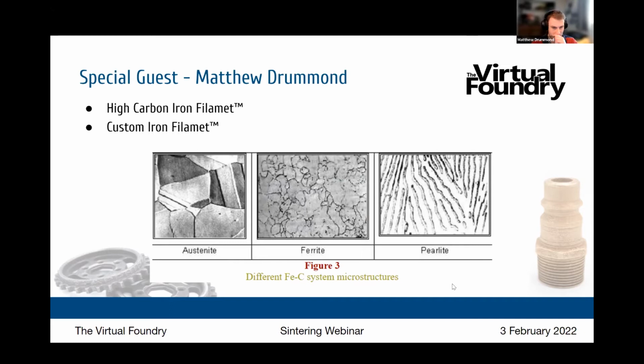As you can see in the picture here, those are the 3 microstructures we're looking at. As far as the research goes, we're trying to essentially make the strongest part possible, which is why we have increased the density of the print itself as much as possible by increasing the flow rate. And then we're trying to get the austenite on the left side. And so if you can go to the next slide.